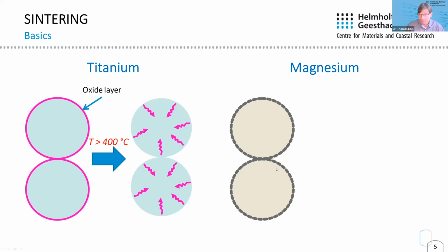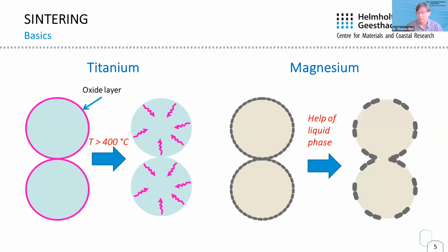But there are some tricks. For example, you can provide a little bit of liquid phase. You can do it by sintering in the two-phase field of an alloy, or you mix different alloys. One is melting a little bit earlier, and this melt then can break up the oxide, and then you get metallic contact between the particles, and the powder particles can sinter, but these oxide particles remain in the material.